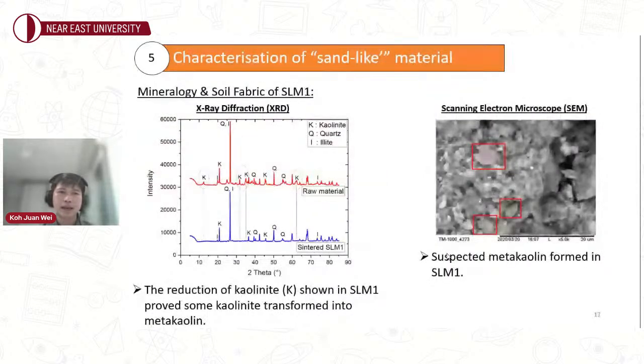And next, we also conducted some mineralogy and soil fabric tests on this SLM1. The first picture over here shows the X-ray diffraction of our product. The red line shows the raw material, and the blue line shows the sintered SLM1. As you can see, the raw material has slightly more K. K represents the kaolinite minerals. After sintering for about 1 hour at 900 degrees C, you can see the K has disappeared. This proves that some of the kaolinite in the clay has already transformed into metakaolin.